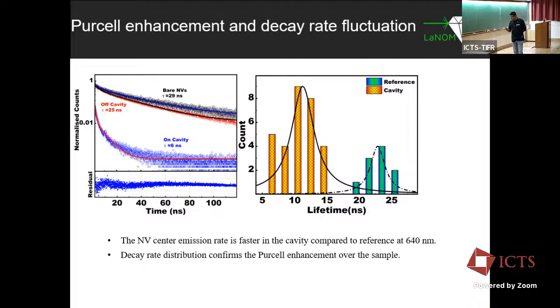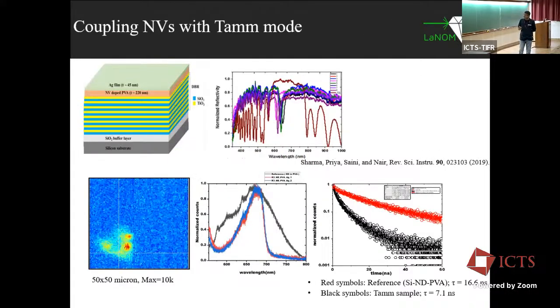So to verify all this repeatability, so we have the single layer. Then I come back to my Tamm structure. We grew this sample in collaboration with IIT Kharagpur. They grew this sample for us, this Tamm structure. You can have these dielectric layers, then there is a spacer layer, which is NV doped, and you have a silver layer. And we got the sample.